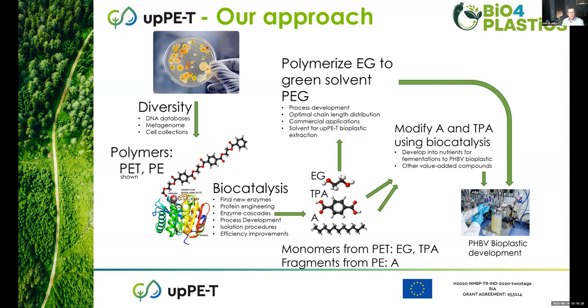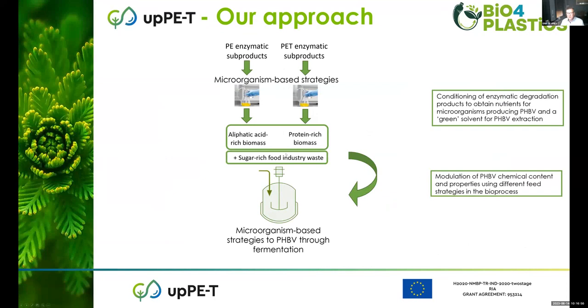The monomers that we achieve from PET are ethylene glycol and terephthalic acid, EG and TPA. What we expect from the degradation of polyethylene are aliphatic molecules with some functionality. These products then are either polymerized into a green solvent or are used in follow-on fermentation steps to create biomass and then ultimately create PHBV. What you see here is that follow-on step where these organic chemical molecules coming out of the degradation of the plastic serve as a feedstock for a renewed fermentation with some type of organism that can grow on these kinds of compounds. From that, we get biomass.